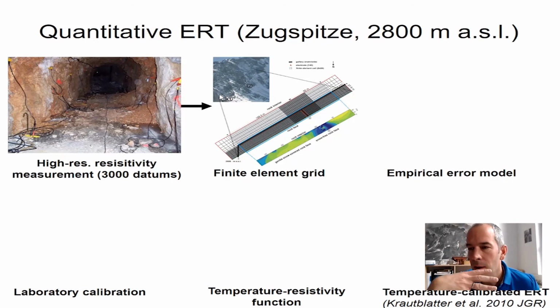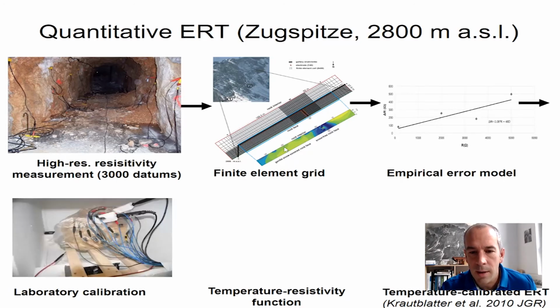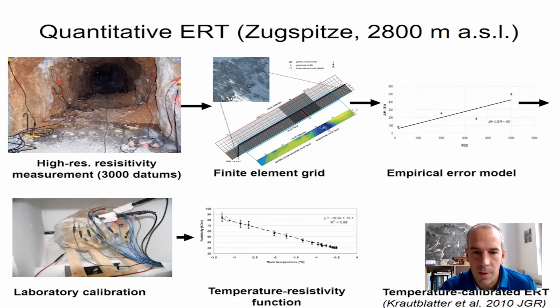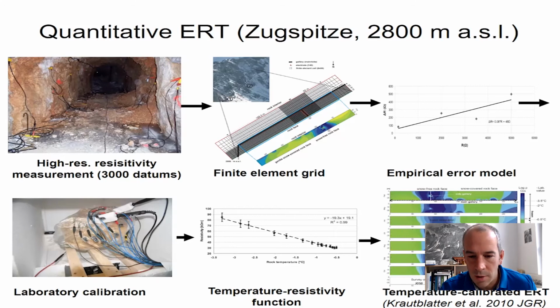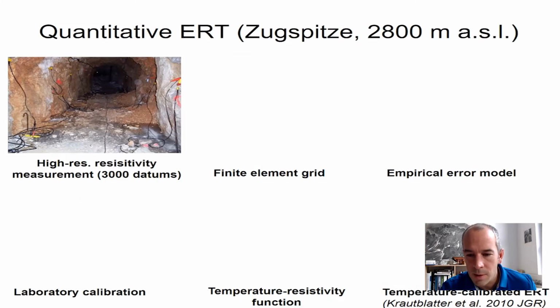30 meters behind this rock face, there's a gallery. This is this gallery here. And here we're having all our electrodes in. So 30 meters behind us in the gallery, there are 140 electrodes. And from this, we make tomographies. And in the tomographies, you see this bluish part is the part that freezes and thaws. Okay, I'll go quickly over that. We take samples to the lab, we calibrate them. We have a curve comparing rock temperature and the electrical resistivity, which we can use to calibrate these curves. And from this, we can then make tomographies to see how permafrost evolves over multiple years. Okay, let's quickly check how they look.